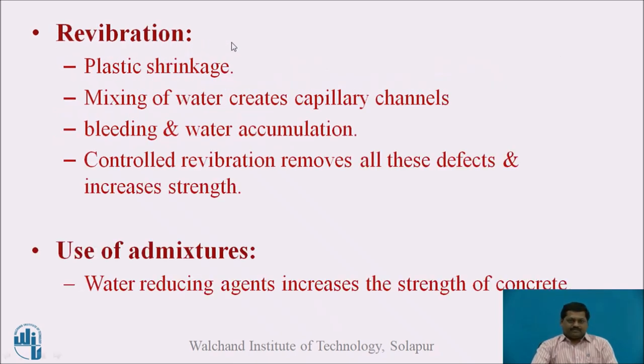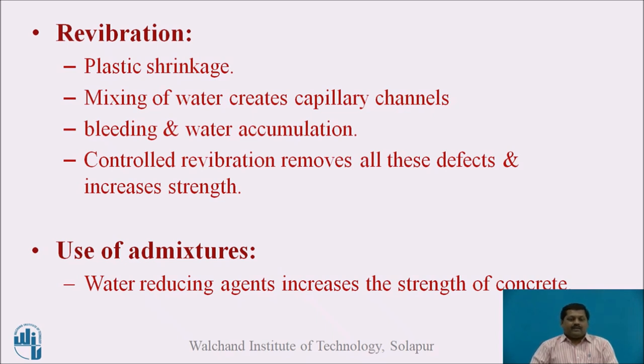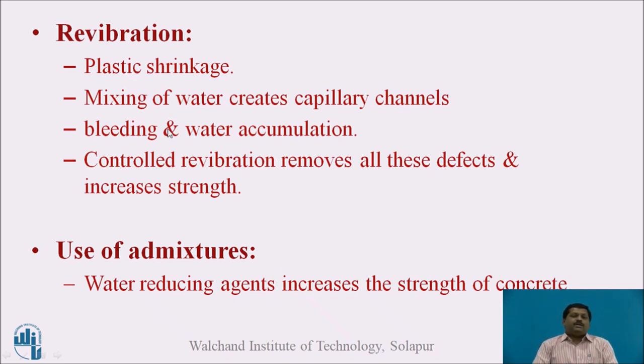The second method is revibration. Since concrete is a cement product, shrinkage cracks — especially micro hair cracks — appear on the concrete surface; these are plastic shrinkage cracks that may propagate further. Mixing water creates capillary channels, and bleeding (separation of water-cement slurry from the matrix) causes water accumulation. All these issues reduce concrete strength. Controlled revibration of the concrete reduces these defects and increases strength.